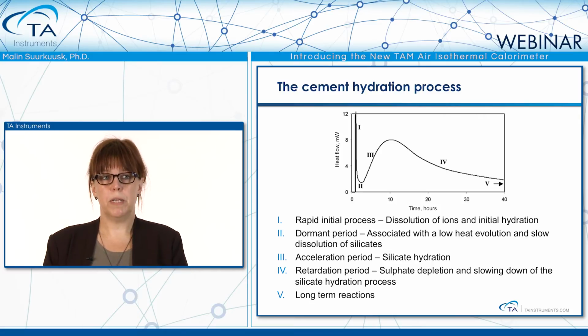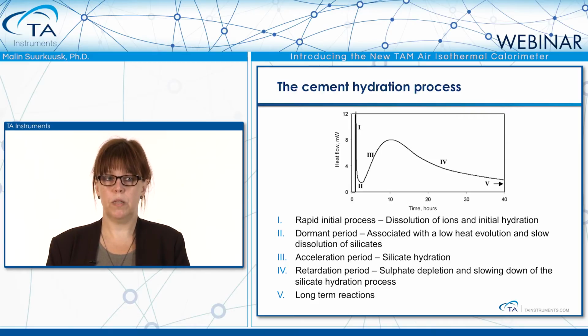So if we look at the cement hydration process, it could be divided into several steps. First, we have the initial rapid process, where the initial dissolution and the start of the hydration process starts. That's very fast and is usually within the first 30 minutes. And then we have the dormant period, which is associated with a low heat evolution and slow dissolution of the silicates.